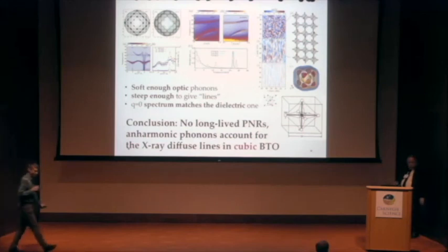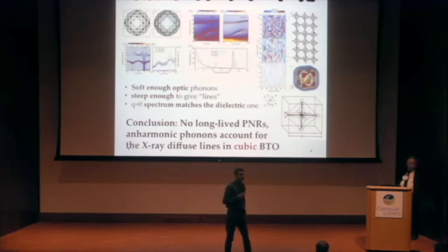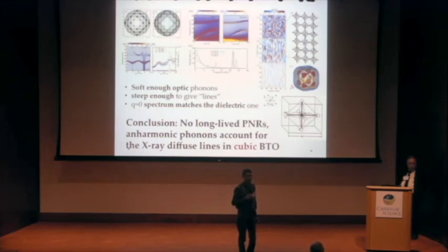Well, in the same vein, we did similar simulations and went very, very close to TC in barium titanate. Of course, it's a first order transition, but you still have fluctuations. It's very interesting that if you're in the fluctuation interval, you get incommensurations and all that sort of thing, but it's limited to an extremely small interval just above TC. So the general conclusion, I agree with you, but if you go into the fluctuation interval, then you have these additional excitations, which are quite strong, but limited to about 1 or 2 degrees. Okay, I take it as a comment.